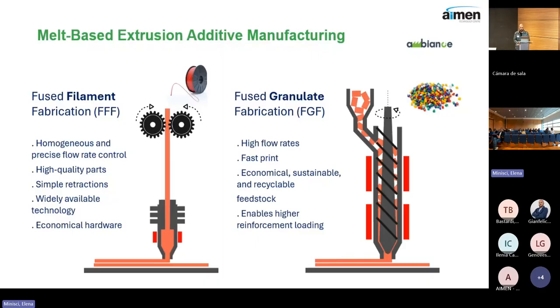And also a very important fact about pellet-based deposition is that you have the ability to include higher fiber content. Whereas on the filament, you have a fiber content around 10-15%. On pellet deposition, you can have from 20 up to 40% fiber content. So this will make much stiffer parts.